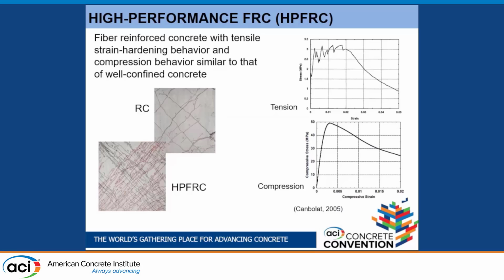Also in compression, these materials behave like well-confined concrete because the fibers restrict or provide lateral restraint against lateral expansion as the concrete reaches the peak or past the peak stress in compression. This tells us that maybe we can reduce the amount of confinement steel or transverse confinement steel when we use these materials, because we start with a material that already has a lot more deformation capacity in compression than plain concrete.